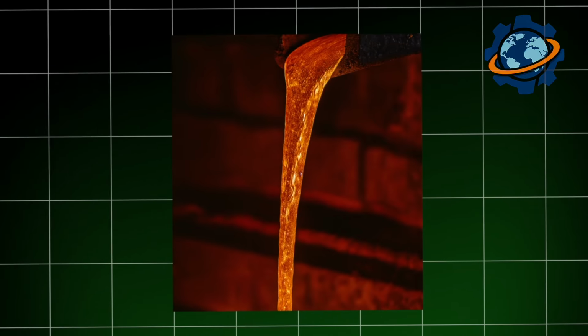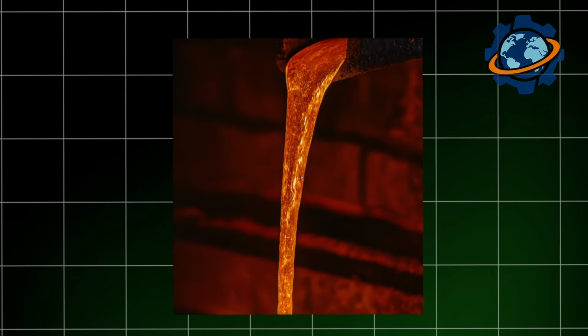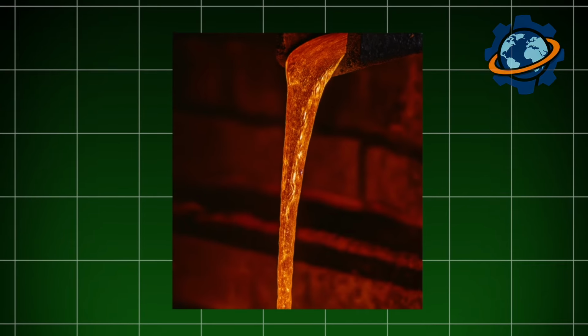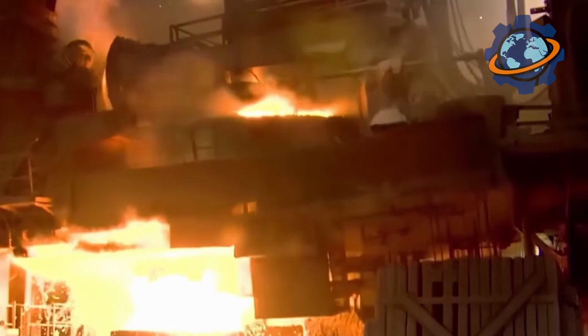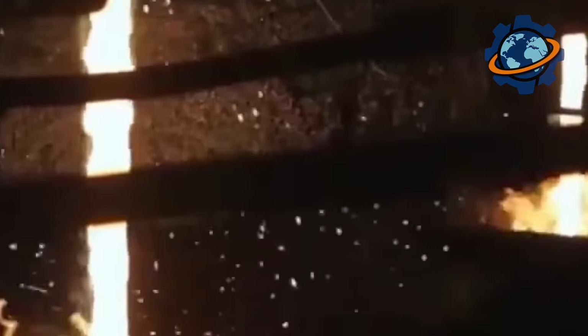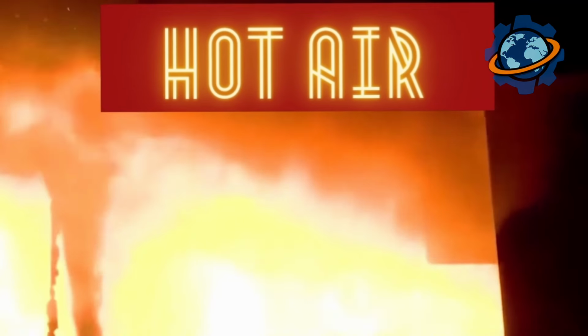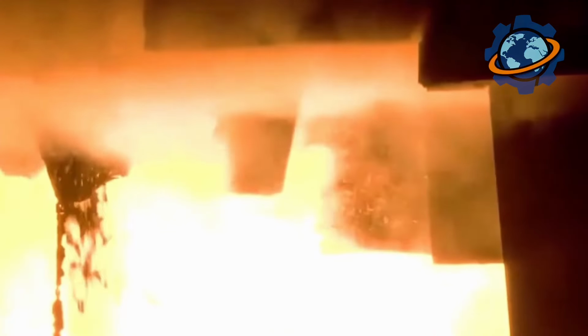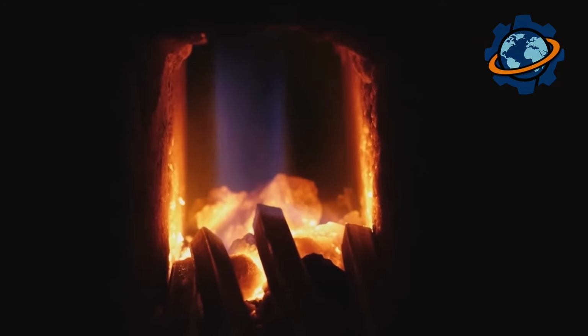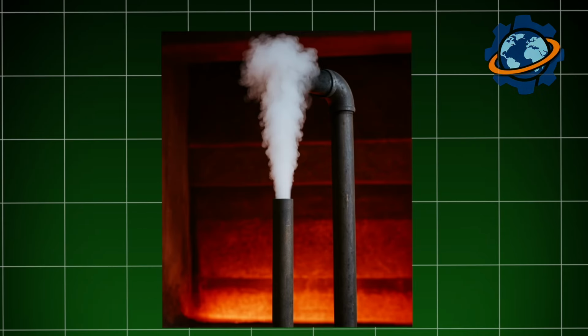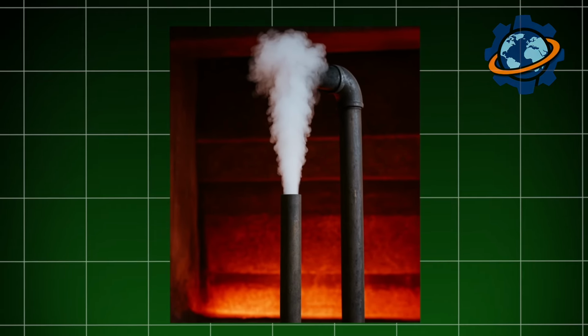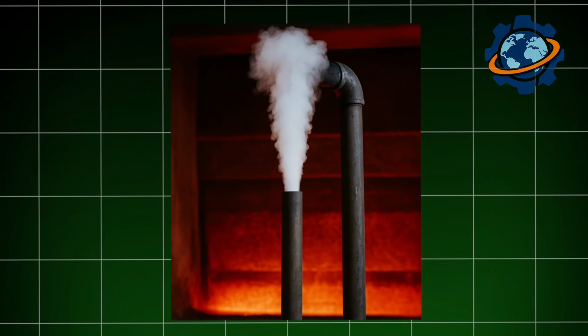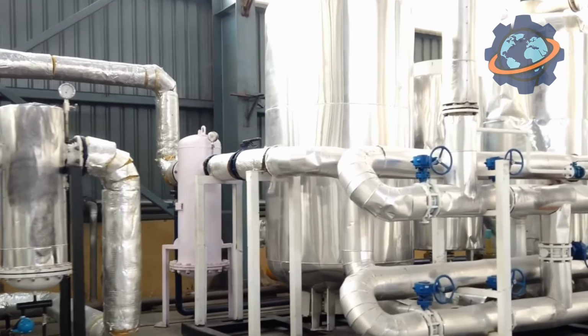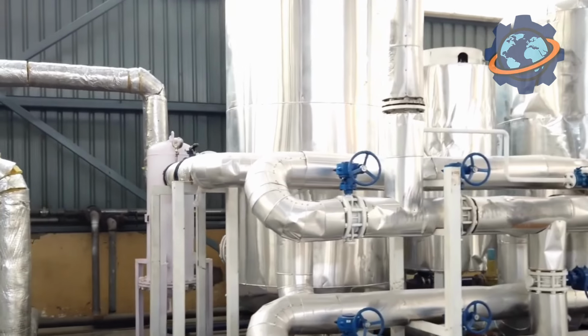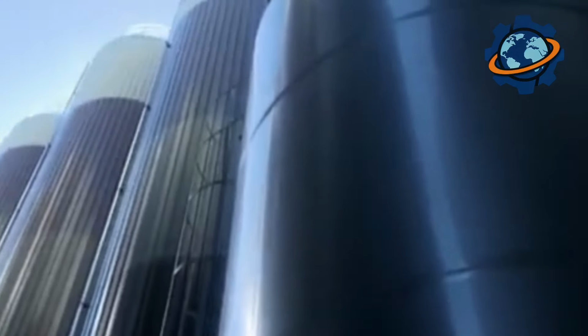At 2,200 degrees Fahrenheit, carbon begins taking oxygen away from zinc oxide. A reduction reaction occurs. But something amazing happens. Zinc doesn't melt. Its boiling point is only 1,665 degrees, but the furnace is at 2,200. So zinc immediately turns into vapor, metallic vapor. Inside the furnace, atoms of gaseous zinc are flying around. The vapors rise up and exit the furnace through piping.